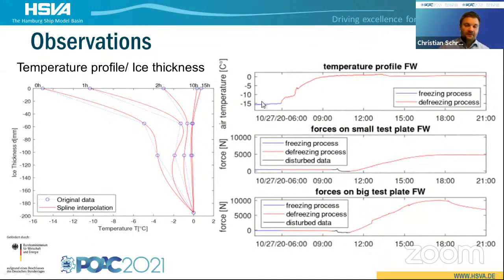If we now come to the test observations, first of all, a bit on the background of the temperature profiles during the measurements. So what you can see here on the top surface, after starting of the defreezing or the tempering phase, we of course had air temperature, so something about -15 degrees at the top layer, and then we had 3 discrete measuring points within the ice, or shortly below the ice. So the water temperature for fresh water was something about 0 degrees, and you can see the time scale up here from 0 to about 15 hours, and you can see how the warm-up phase came through the top layers of the ice further down until it went relatively straight from the top surface down to the water temperature.